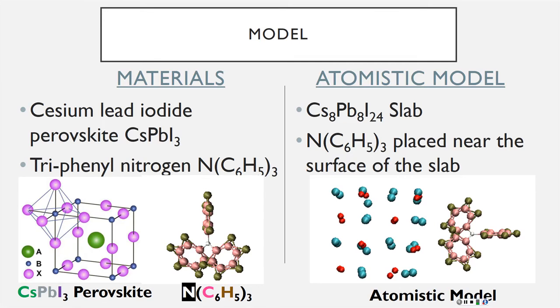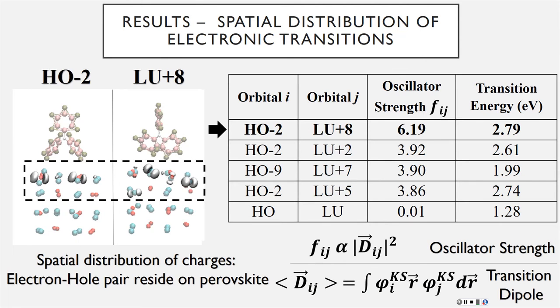And then for the input atomistic model for VASP, I chose a Cs8Pb8I24 slab. So it's a couple unit cells that has a surface, and then it extends periodically into the structure to mimic bulk characteristics. And then we just place the dye molecule. It's not physically connected, it's just placed pretty close to the surface of the perovskite. And just to note that all of these conclusions were done at a ground state optimization, so it's all 0K, so there are no thermal fluctuations with these results here.